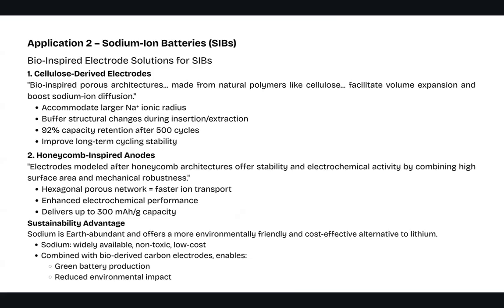The second application of bio-inspired electrodes is on sodium-ion batteries. First, cellulose-derived electrodes. They have bio-inspired porous architectures made from natural polymers like cellulose, which facilitate volume expansion and boost sodium-ion diffusion. It accommodates the larger Na+ ionic radius and buffer structural changes during insertion and extraction. It shows 92% capacity retention after 500 cycles, and also improved long-term cycling stability.